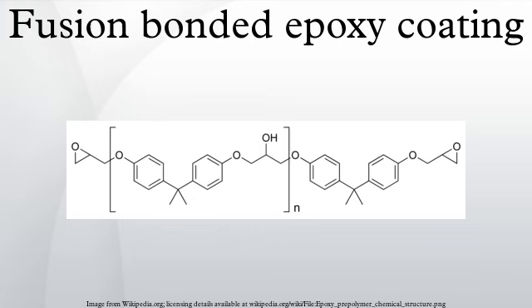The molten extrudate then passes between cold rollers and becomes a solid, brittle sheet. It then moves to a kibbler, which chops it into smaller chips. These chips are ground, using high-speed grinders, to a particle size of less than 150 micrometers. The final product is packaged in closed containers, with particular care given to avoid moisture contamination. Normal storage temperatures of FBE powder coatings are below 25 degrees Celsius in air-conditioned warehouses.